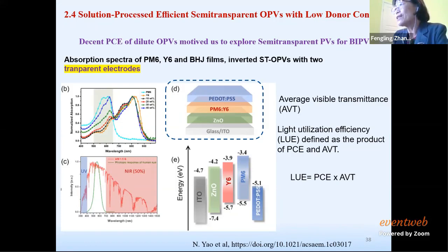And there are different parameters to define the performance of the transparent OPV. One is power conversion efficiency, but we are not only concerned with it, because it will definitely be lower than an opaque device because it's a single pass of the photon. Another is average visible transmittance, because we are more concerned about people's eyes, which are most sensitive around 550 nm, something like that. Then we should enlarge the transmittance in that part. For the range of photons people are not sensitive to, we can absorb more, but in this part we should not absorb more. Therefore, we use another parameter to define the performance of the device. It's the light utilization efficiency, the product of the PCE and the average visible transmittance.